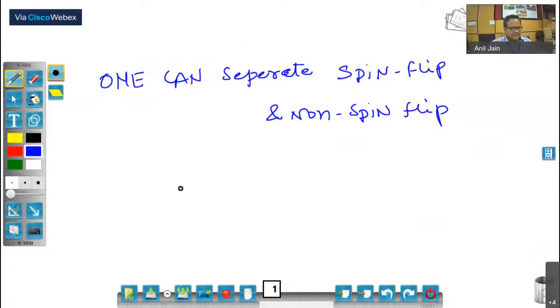It means one can separate the nuclear and magnetic scattering. So suppose you have the sample, and you polarize its spin along the z direction, and you are working in the horizontal scattering geometry, and your initial polarization of the neutron beam is along the z direction, then all your magnetic scattering will go to non-spin flip. Please keep this in mind.